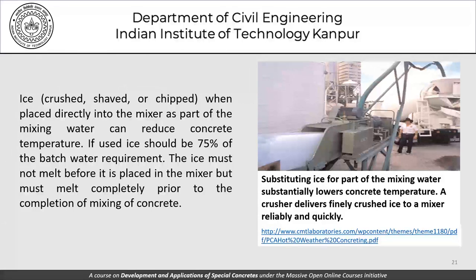Ice can be substituted as part of the mixing water to substantially lower concrete temperature. A crusher delivers finely crushed ice to the mixer reliably and quickly. Crushed, shaved, or chipped ice placed directly into the mixer should be up to 75 percent of the batch water requirement. The ice must not melt before entering the mixer but must melt completely prior to completion of mixing — ice must not remain in solid form after concrete has been mixed.